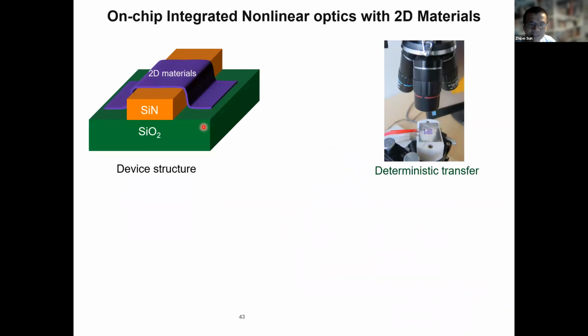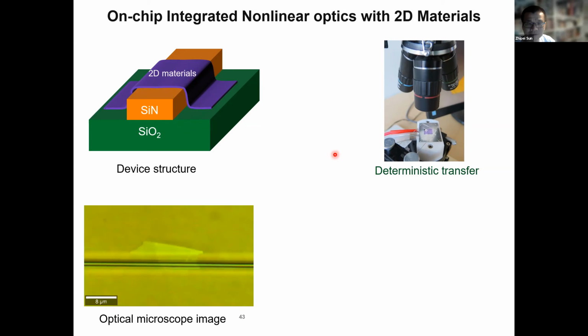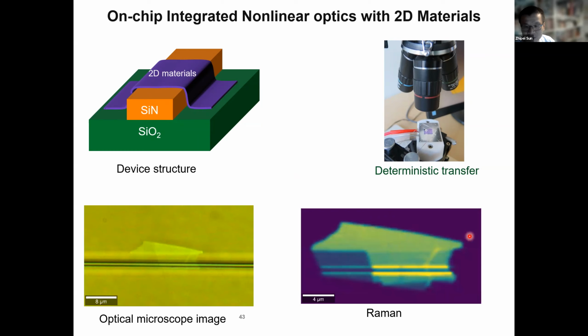We also integrated 2D materials for on-chip nonlinear optics. To realize devices like this, we have developed a deterministic transfer technology for 2D materials. This is the 2D material transferred on top of the waveguide. From the Raman image here, you can clearly see that the flake is transferred on the waveguide, and the overlapping area between the flake and the waveguide is around 15 microns.